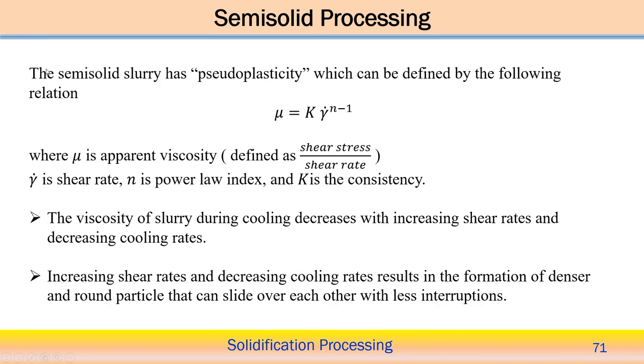Now, semi-solid might have some kind of pseudoplasticity, which can be defined by this particular relation: the viscosity equals k times the shear rate to the power n minus 1. n is the power law index, and k is the consistency constant in this particular case. The viscosity is represented in terms of the apparent viscosity, which is defined by the ratio of the shear stress to the shear rate.